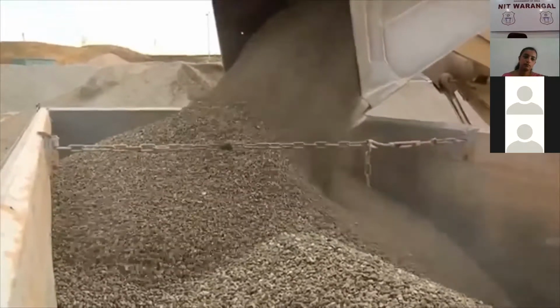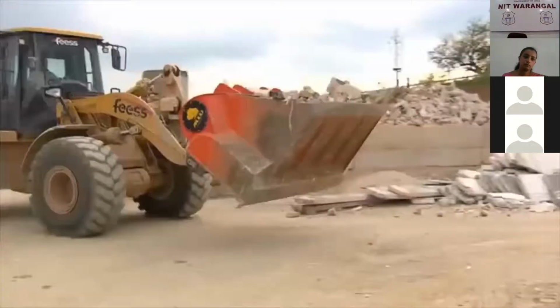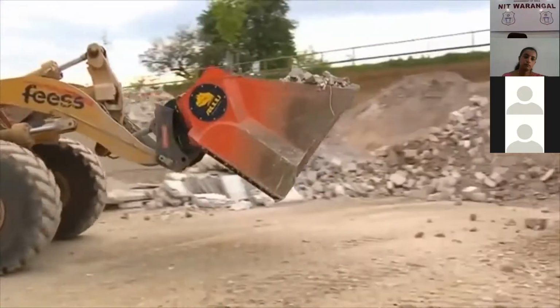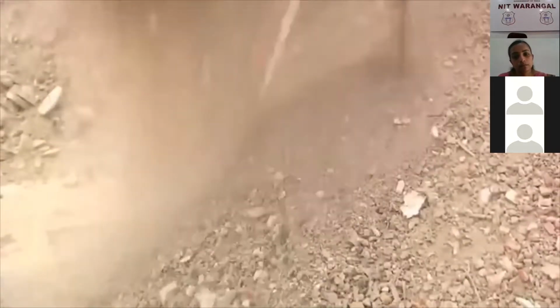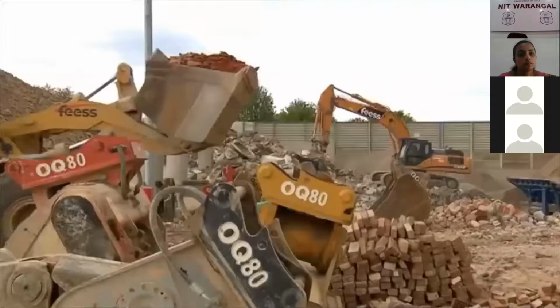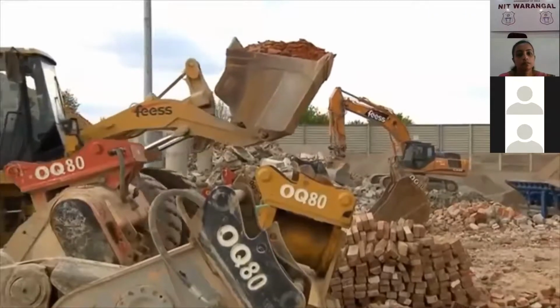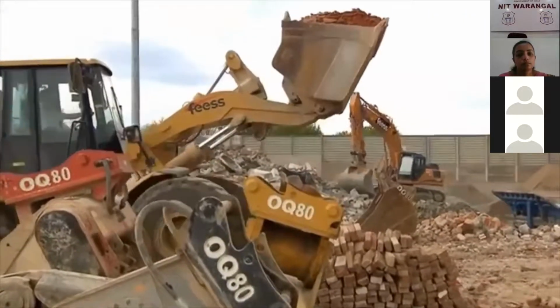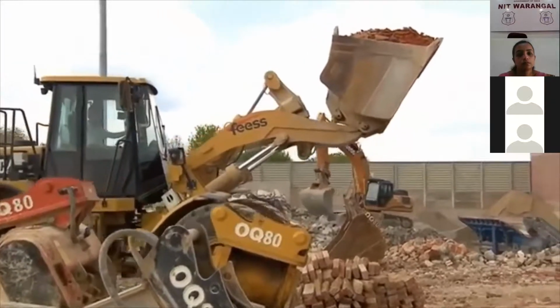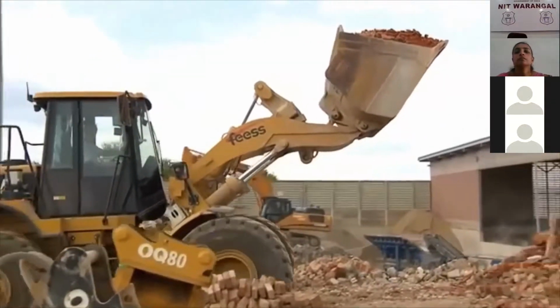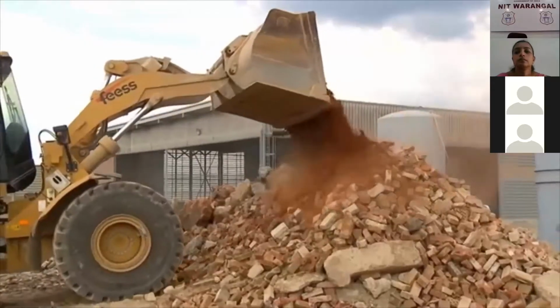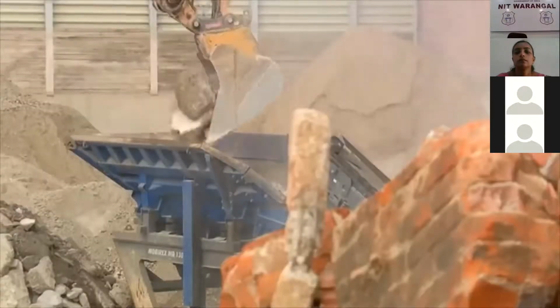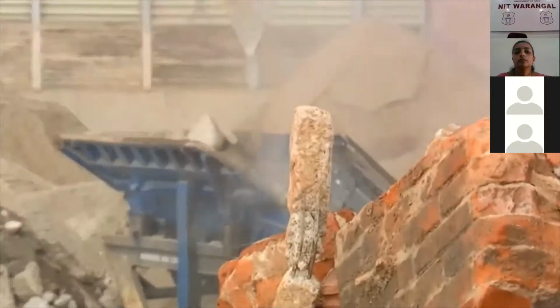The Swabian building material experts also process masonry and even roofing tiles. Using a special screener located in the bucket of a wheel loader, material can be separated from plaster remains, small particles of wood, and sheeting. The resulting fraction also makes its way through the crusher and into the recycled concrete. Because of its careful gathering and perfect sorting, Feess is able to recycle 80 to 90% of the demolition waste. That's around 1/3 more than usual.